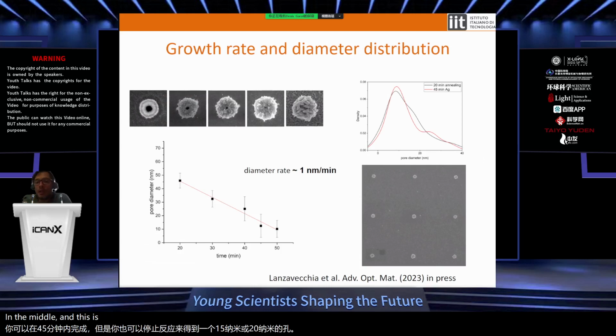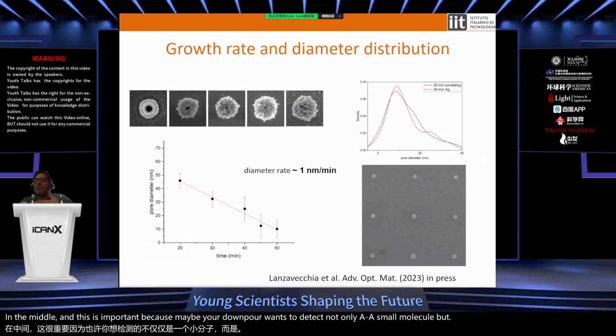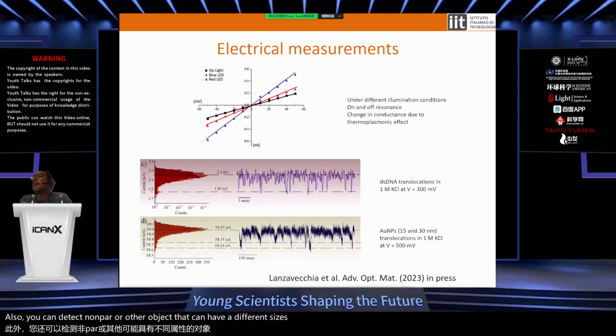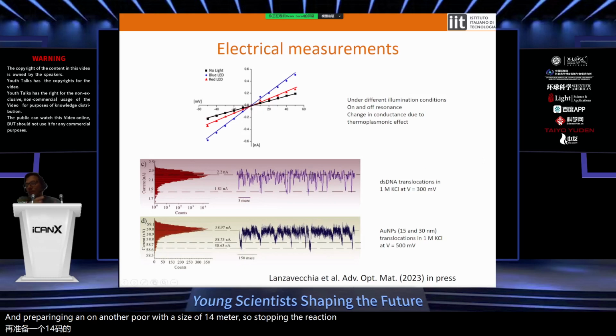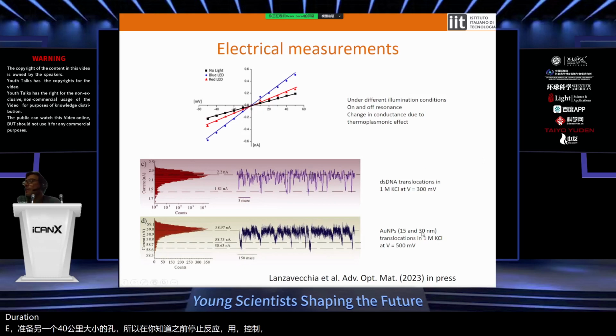And this is important because maybe your nanopore wants to detect not only a small molecule, but you can also detect nanoparticles or other objects that can have different sizes. And in fact, we demonstrated this platform both for the detection of DNA, playing with a very narrow pore with a size of 4 nanometer, and preparing another pore with a size of 40 nanometer, stopping the reaction earlier, with this controlled duration. We also performed the detection of a mixture of nanoparticles with different sizes.